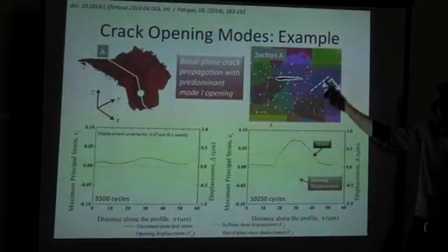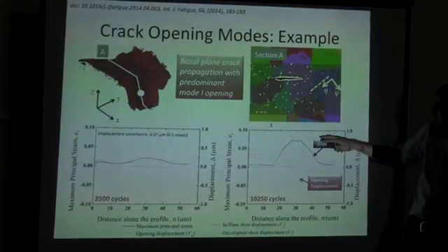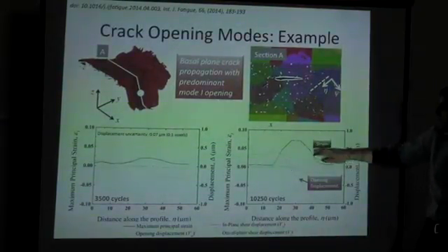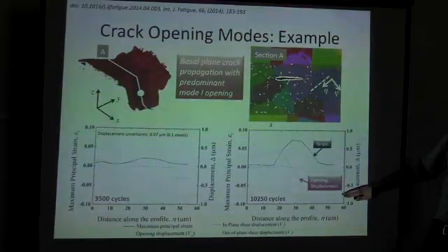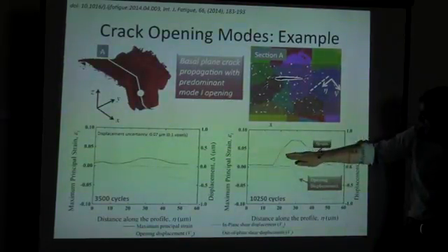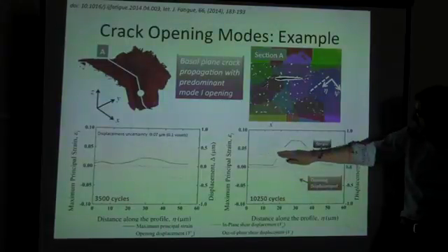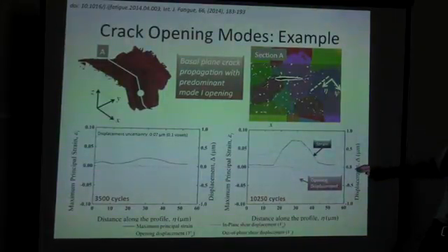This is what we get when we look across the crack. We just do it in terms of the gradients. We get strain, apparent strain. That's telling us we found the crack. And essentially this point here is showing that we get a displacement change across the crack of the order of around about a micron and a bit.